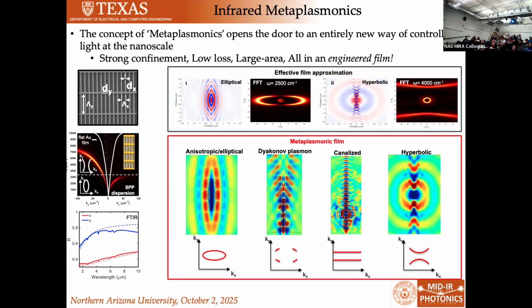So then the challenge becomes, how do you get your optoelectronic device into a length scale that small? Your superlattice absorbers require many periods to get that miniband effect. So we started thinking about new types of device architectures that we can put into 10, 20, 30 nanometer spaces, such as quantum dot or quantum well type structures where we couple an optical transition to this very strong optical mode. Or it could be new ways of generating optical transitions in semiconductor materials that typically wouldn't be used because they're not particularly efficient. But if you put them in the near field of a plasmonic mode, you might be able to make them function.